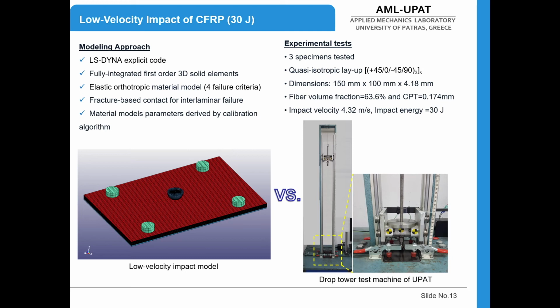In this case, we have simulated this experiment, and of course, we have used here the optimized material parameters. We have used LS-DYNA explicit for the simulation. Again, as in the former work, we have used fully integrated first order 3D solid elements, an elastic orthotropic material with the failure modes that we have already described, and of course, fracture-based modeling of the interlaminar failure, and the material model parameters delivered by the calibration algorithm.